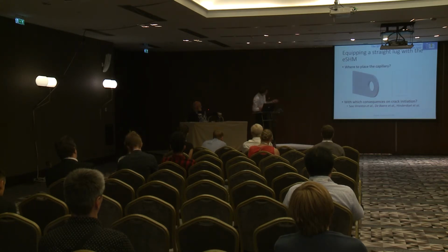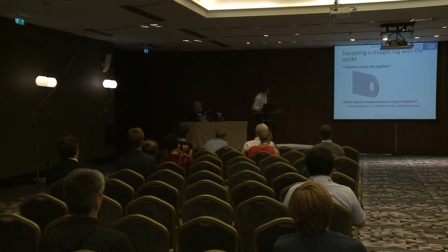that the crack would develop from the capillary, and to avoid that they have performed experimental investigations. They have shown for all the samples that they tested that provided this distance, the A distance between the bottom of the capillary and your surface or critical zone, is higher than 3 millimeters, you have no risk anymore of crack initiation at the capillary. And in all my simulations, whatever the diameter, this distance was always 3 millimeters. Thank you.